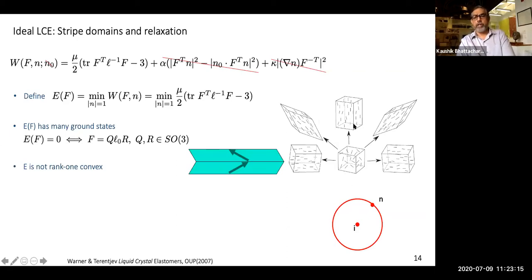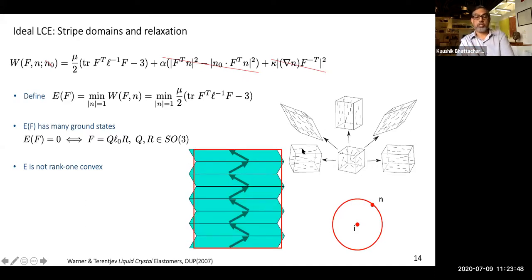And consequently, you can very easily show that this is not convex, and in particular, it's not rank-1 convex. So what that means is that I can take two states and make a state where one part of it is in one state, the other part of it is in the other state, and the deformation remains continuous, or the deformation remains compatible across this interface. What that allows me is not only to have these ground states, but additional ground states. And basically what I'm doing is a relaxation by creating fine scale oscillations in this material.